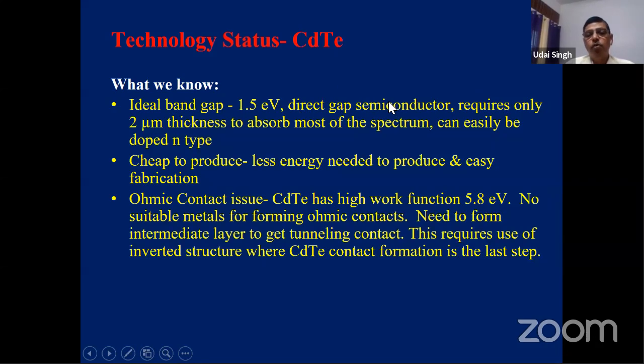In CIGS, copper indium gallium selenide, or copper zinc tin selenide, there are 4 materials. So controlling the composition is a difficult task in those materials. Composition control is one of the major challenges there. But here, with only 2 materials, you can have quite good control. It is cheap to produce, needs less energy to produce, and is easy to fabricate.